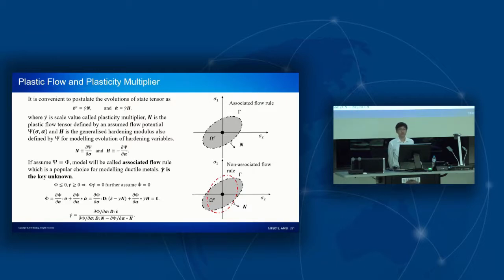Now we have defined the direction of the plastic strain, but we also need to define the increment, like the magnitude of increment of the plastic strain. In order to do that, people use another condition called the consistency condition, which is that the change of the yield function is equal to zero. And by using that assumption and the assumption of the additive decomposition of the total strain, we can end up with a bottom expression to explicitly derive the magnitude of the plastic strain. And usually people call this the plastic multiplier. Other material state variables can all be written as a function of the plastic multiplier. So once we have derived the plastic multiplier, then we can update other state variables accordingly.